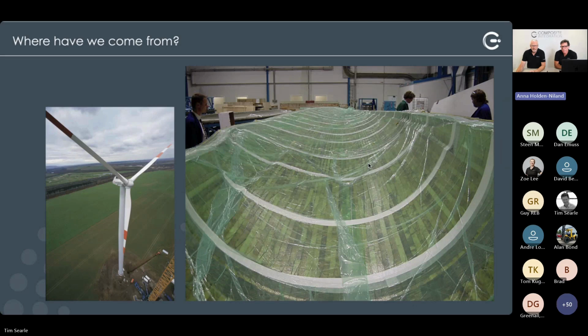At the time, blades were much smaller than they are today. A 40-meter blade versus the sort of 115, 120-meter blades that we're currently working on. At the time, we thought this was a huge infusion, but a lot of the parameters seemed to work. We didn't at the time get in any way obsessed or worried about degassing of the resin. We had some quite clever strategies to enable the resin to flow into what was still, at the time, quite a big part. And thousands of blades were made like this. You can see, if I haven't mentioned this already, that this is largely a wood and carbon blade with glass skins. But in this, we needed to scale and we needed to automate. And this really did pave the way for what we call direct infusion.